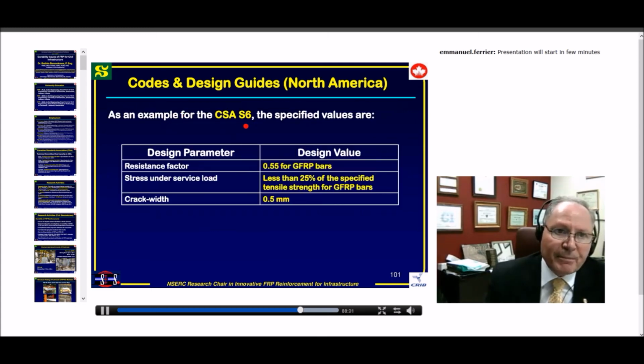Some example in the S6 code, this is the Canadian Highway Bridge Design Code. Resistance factor, we have 0.55 for GFRP. This means by using the characteristic strength, which is the mean minus 3 times the standard deviation, this is the 99.9 percentile, which means one value over 1,000 specimens will be less than the characteristic.